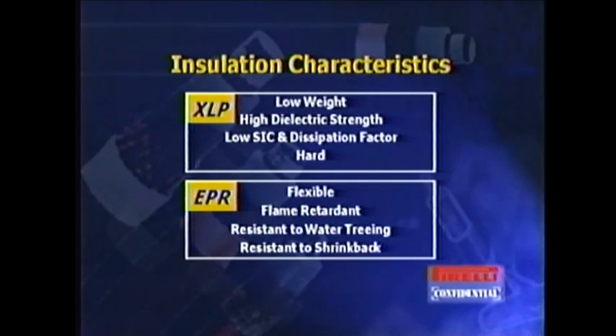EPR, on the other hand, some of its benefits are that it's very flexible as compared to cross-linked polyethylene, meaning that in installations where you have large conductors or maybe tight bends, EPR might be a better choice. It's also inherently flame retardant, or at least more flame retardant than cross-linked polyethylene. So where you have CT-rated designs, you might see EPR insulation systems.